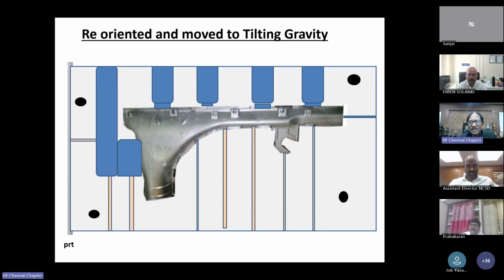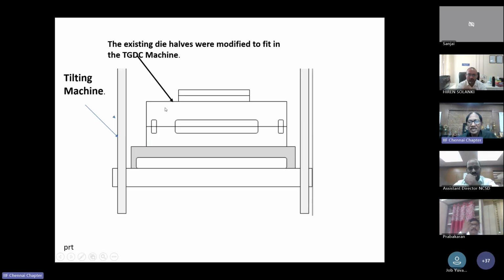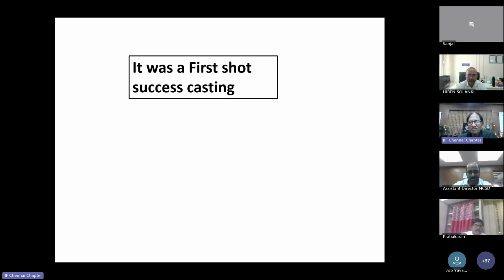This is the redesign of the casting. Full shot. You pour from here, only hardly. You pour, all the metal enters. You put up a pouring bowl over there. Just tilt it. Have a lot of air vents. So the metal comes from all the places right away from the mouth. This is the die. The same die was modified, removed all the risers and fitted into the machine, and the whole machine was tilted and poured. It was a first shot success.